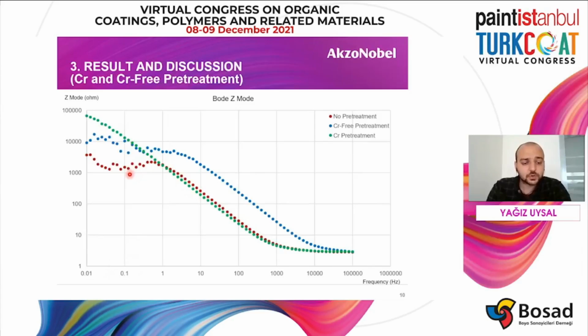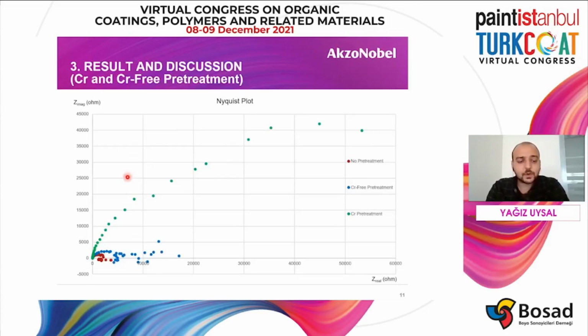This complex corrosion mechanism is also seen in the Nyquist plot, as shown in the blue and the red one, and also the difference in the chromium pretreatment one can be seen clearly when it's compared to the other ones. Chromium pretreatment one has the highest imaginary values and the largest diameter, and the higher imaginary values indicate the higher capacitance, and this leads to effective corrosion resistance.